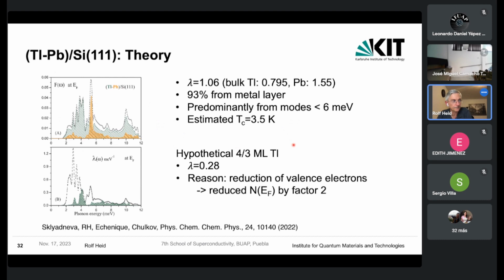We've also looked at a hypothetical system, namely just replacing all the lead atoms by thallium. But then we find that the coupling really drops significantly, and the main reason is that thallium, the neighboring element to lead, essentially reduces the number of electrons in the system, and that leads to a shift of the Fermi surface to a region which is unfavorable, where the density of states is significantly lower, and that has an immediate impact on the overall coupling strength. So we would not expect that a pure thallium layer is superconducting.